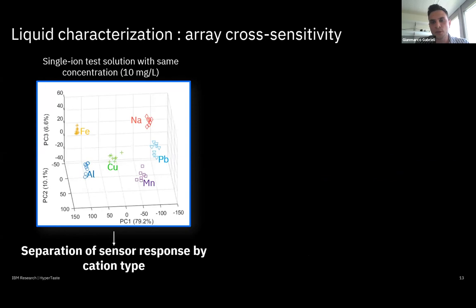So for the liquid characterization, we have first tried to characterize the array cross sensitivity. So we have tested the same concentration of different ions, so in six different solutions. And we have seen in the principal component analysis that we were able to completely distinguish the six different liquids. And this difference is due to the cationic type inside the liquid.